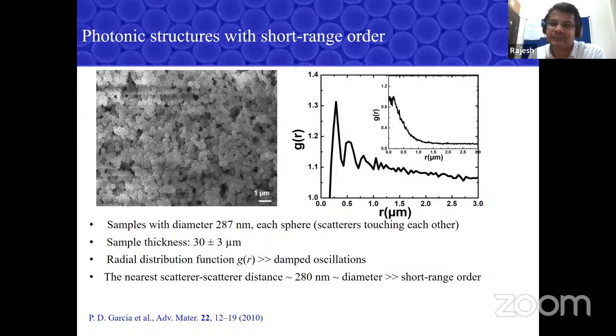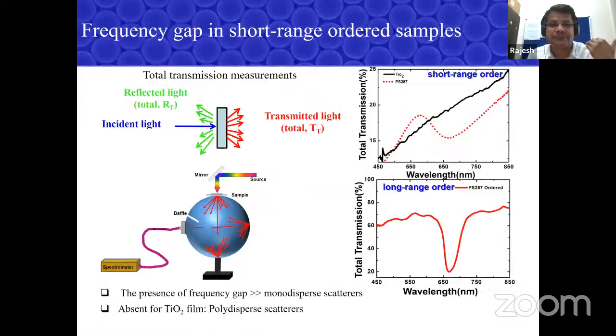And if you look at white powders like chalk powder, paracetamol tablets or titanium powder, you don't see any such oscillations because there are no scatterers connected adjacent to that. So this confirms that there is a bit of short range order present in this system. And then we wanted to understand what happens when you launch light into the system. And there was a very surprising result for us.